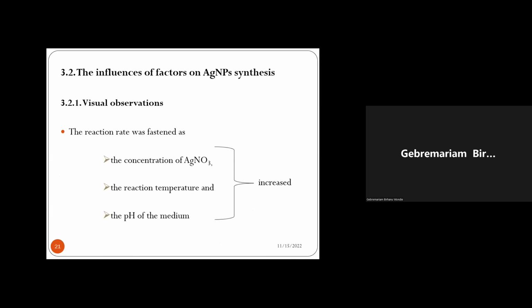So when it comes to the results and identification, the first result was that we checked the presence of different phytochemicals in the plant extract, and most of the phytochemicals except the alkaloids, steroids, and terpenoids were present. These are responsible for the stabilizing or capping and antioxidant effect of the nanoparticles, and helped the successful synthesis of the silver nanoparticles. Mainly the phenols and flavonoids are responsible for the capping and stabilizing effect.